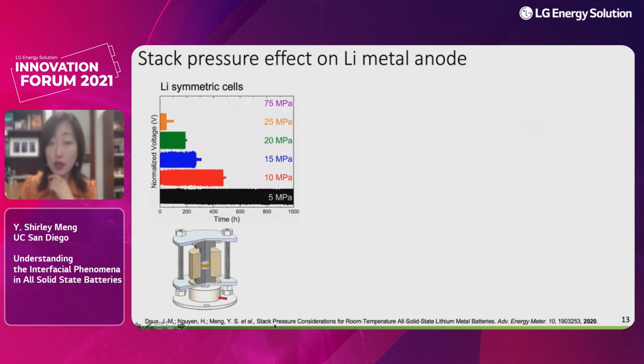My postdoc, Dr. Jean-Marie Doe, initiated systematic studies with pressure-controlled load cells to investigate lithium symmetric cells. It's a very interesting observation that whenever we go below 5 megapascal—we also have 2 megapascal and 1 megapascal data—whenever you're below 5 megapascal, you can cycle lithium in the symmetric cell very long term.